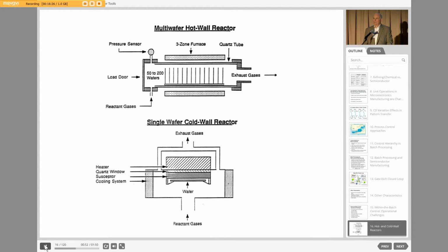And the wafer size has actually grown over time. Later after they had 4-inch wafers, they went to 6-inch wafers, then 8-inch, then 12-inch, which is currently pretty much the max size, although interestingly enough, there are lots of 8-inch fabs out there and processing units that people use. They can make a profitable product, and as someone said, they've all been depreciated, so they actually have a low cost of ownership as well. But basically, this is a way in which we get much better control of what happens on the wafer.